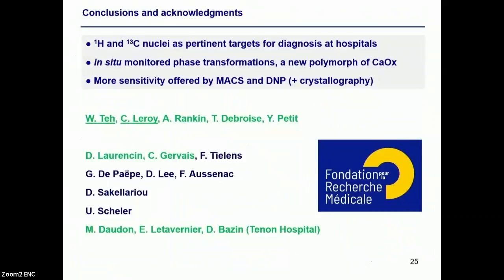So that's the end of my talk. These are the conclusions. I hope I have shown you that yes, proton and carbon nuclei are good targets for physicians, especially nephrologists, and we have a very nice collaboration now. It's possible to follow in situ the phase transformation of all the calcium oxalate hydrates, and we have shown that this is subtle, and we even demonstrated the presence of a new polymorph, which had been proposed based on DFT calculation.